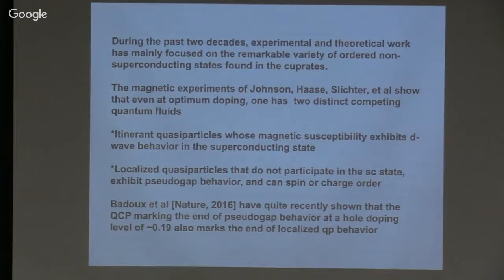So most of the experiments since the mid-90s have really focused on the pseudogap. But a little thought and a lot of experimental work shows that the pseudogap state is the state of the local moments that are there coexisting with the itinerant electrons. You have two fluids throughout almost the entire doping range of the cuprates. One fluid are the local spins, which then order in the pseudogap state. They have to get rid of their entropy somehow, so they do so by going into the pseudogap state. The other are the itinerant electrons, and they get rid of their entropy by going superconducting at lower temperatures.